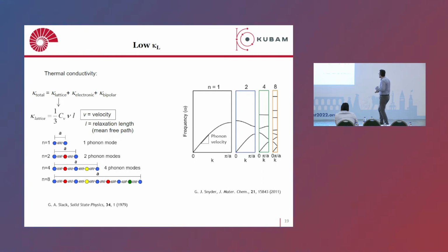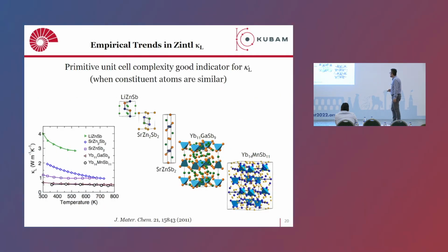In this way, if you just increase the size, if you increase the number of atoms, different types of atoms, you basically have larger unit cells, which leads to more low velocity optical modes that lowers substantially your thermal conductivity. This is nicely experimentally shown for a particular family of materials, which is called the Zintl phase. So you can see that this is lithium zinc antimonide, strontium zinc antimonide, all the way to ytterbium manganese antimonide. Similar materials, the atoms are similar, but the difference is the complexity.